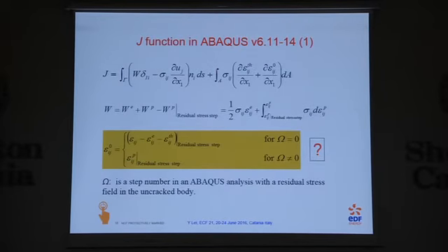But for this case, raw J is path dependent. Abaqus is path dependent, but different from raw J. But my program can exactly copy Abaqus's raw method. If I change my calculation into the correct function, it is path independent. So this gives some idea that the equation I guess is exactly the same, so I use the same method. But you can imagine I have to calculate many cases. Okay, then what did we find?